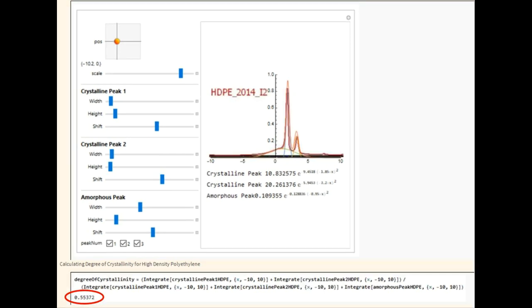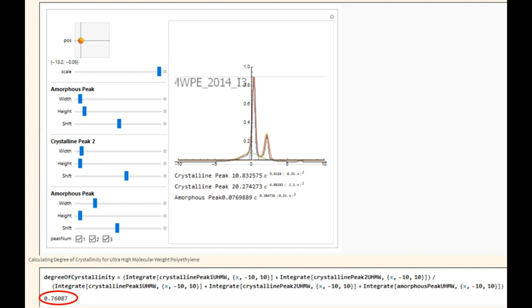Similarly, the expected value for degree of crystallinity for high-density polyethylene is 48% to 69% crystallinity, and Mathematica peak fitting obtained a value of 56% crystallinity. Finally, ultra-high molecular weight polyethylene has an expected value of 75% to 77% crystallinity. Mathematica peak fitting showed a value of 76% crystallinity.